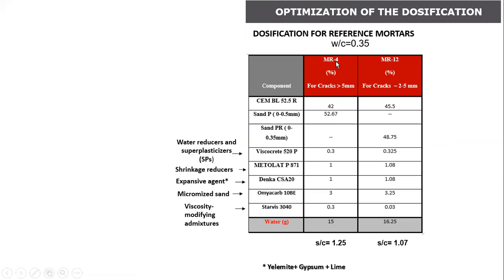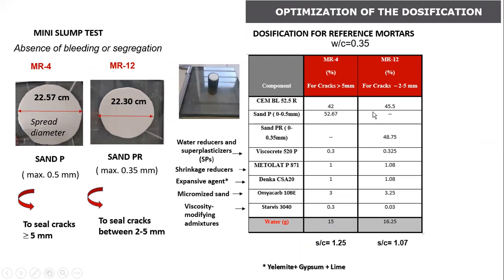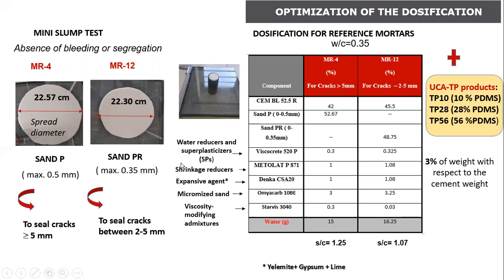The first one, MR4, prepared with the sand P, was specially designed to seal cracks equal to or higher than 5 millimeters, and the other one was specially designed to seal cracks with lower thickness. In both cases, we have used a water-cement ratio of 0.35, and the sand-cement ratio was around 1, slightly higher in this first case. As you can see, we have used several types of chemical admixtures to improve the different properties. And we have modified these parameters until we obtained the reference mortar with the desired viscosity and the desired fluidity. Once we have these mortars, we have incorporated the InnovaConcrete products with a different proportion of polydimethylsiloxane, and we have incorporated these products into the fresh repair micromortar during the mixing procedure in a proportion of 3% by weight.